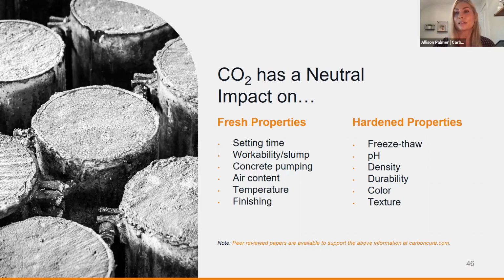Just to reiterate, CO2 has a neutral impact because we're injecting about 1 pound of CO2 for every cubic yard of concrete, which is about 4,000 pounds of material. That 1 pound of CO2 just wouldn't have an impact on temperature. It'd be like throwing a handful of ice cubes into the back of a freight truck and expecting it to cool off.